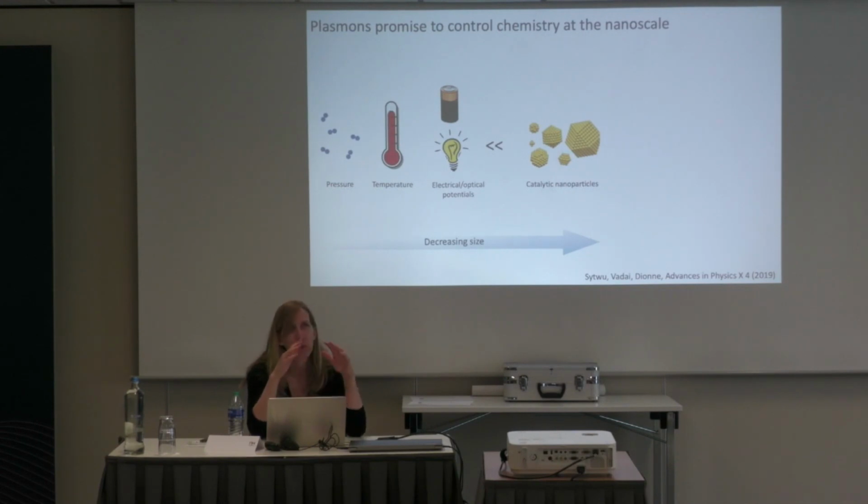But basically, what you'll see in some of the videos is that the low coordination number sites matter a lot for catalysis. Whenever you have sharp tips, that's where the molecules tend to be splitting with the highest rate. So you get a lot of kinetically preferred activity at those low coordination number sites. And the faceting determines what precisely that low coordination number site looks like.